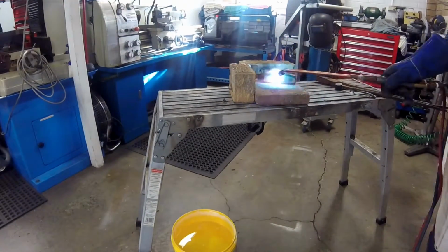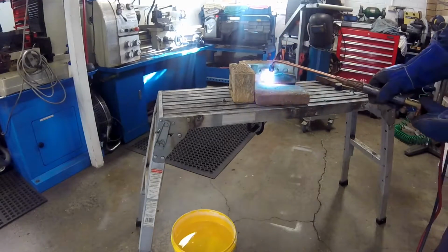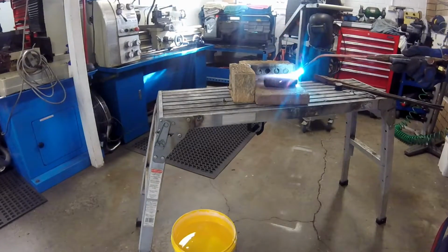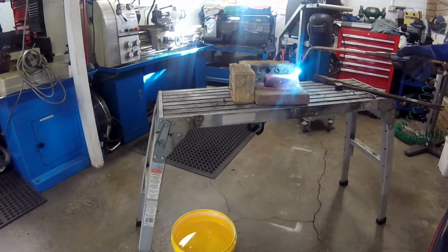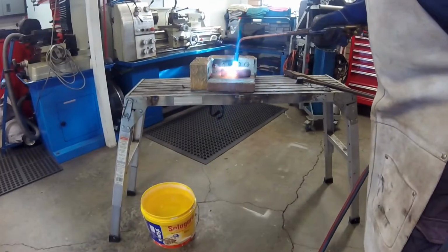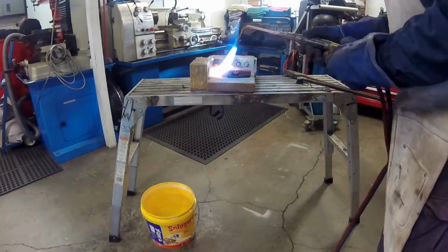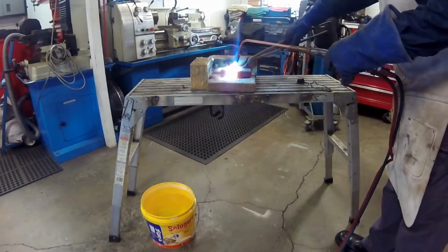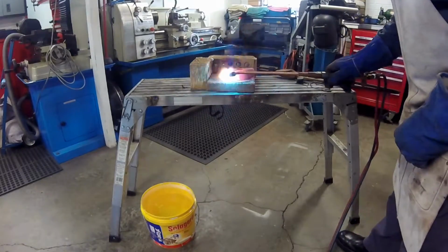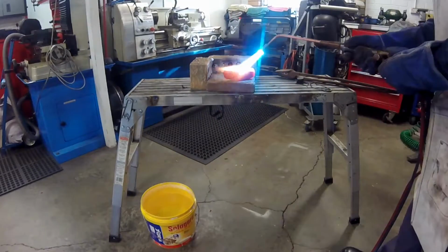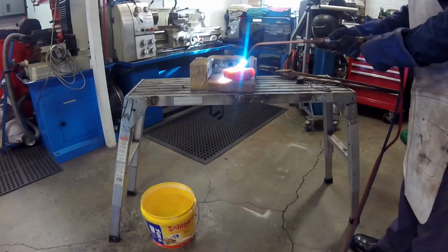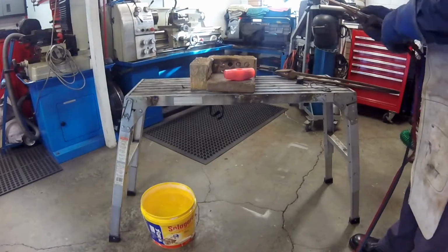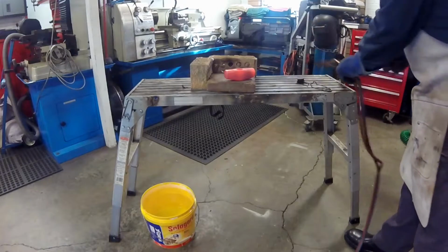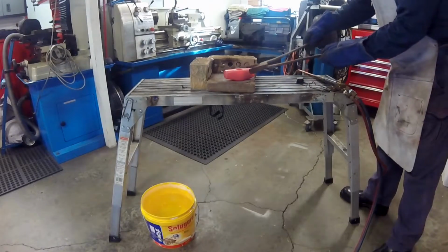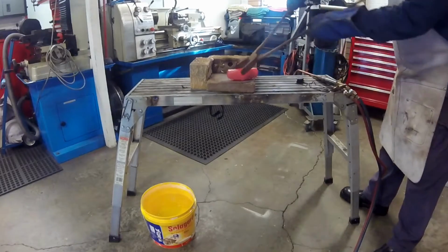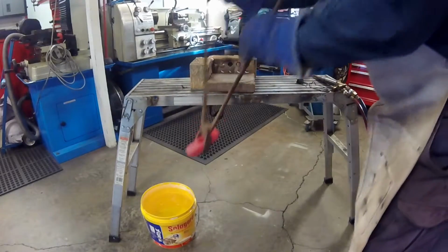Here I'm using an oxyacetylene torch to treat the hammerhead, and I am aiming for a temperature of 900 to 1000 degrees Celsius, or about 1650 to 1830 degrees Fahrenheit, where the steel will take on a cherry red colour. This takes a while, and it is important to keep moving the torch and the hammerhead so that the heat is evenly distributed. In the end, I get the colour to orange red, which is about 1100 degrees Celsius, or about 2010 degrees Fahrenheit. Then I put the torch out, pick up the head with long handled tongs, and plunge it into a bucket of water to quench it.